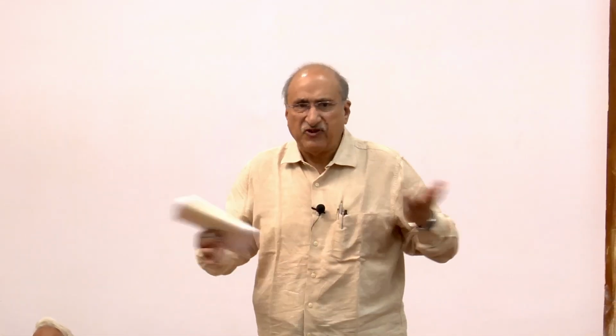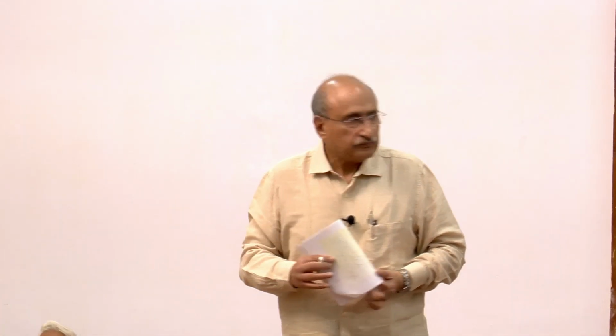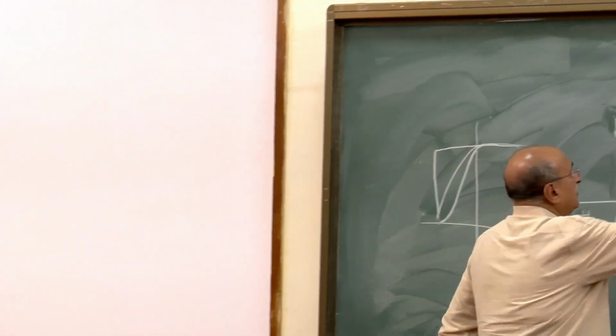We have worked on materials which are considered excellent materials, but only because of their temperature dependence, they could not be used. The temperature dependence was very bad. Just a change of 10 degrees and the properties are totally different. And the last thing that I have not mentioned